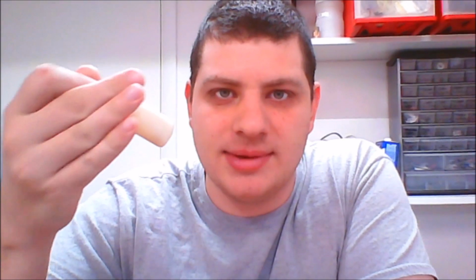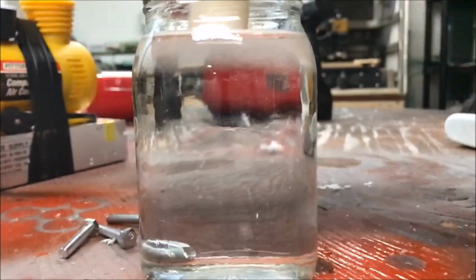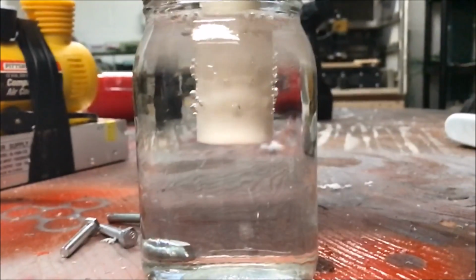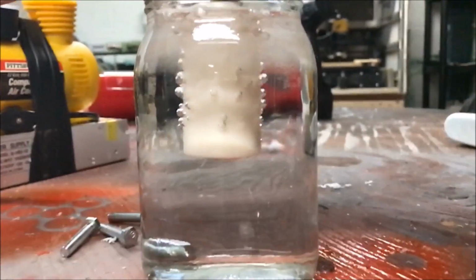I did another test. I hooked up the air compressor to this and then set it in a clear jar of water with my camera aiming at the side. Using that, I was able to see where the bubbles were escaping. And the results were super interesting. As expected, the controls were still the same. Air was escaping from everywhere on here. The cold vapor had exactly the same problem. The rate may have been slowed down a little bit, but it was still completely porous.